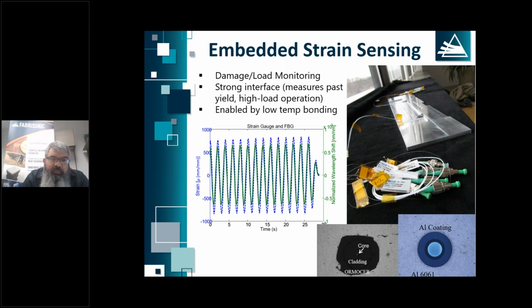We embedded some fiber optic strain gauges into an aluminum plate that they have a lot of history of the design and analysis of. And it was interesting, we were able to actually collect data while it was being cyclically loaded. We were able to see cracks appear and actually watch the plastic zone of the crack as it approached the fiber optic sensor. Of course, at some point, the fiber optic sensor broke, but it was interesting that we could actually watch that plastic front move closer and closer as the crack evolved in the part.